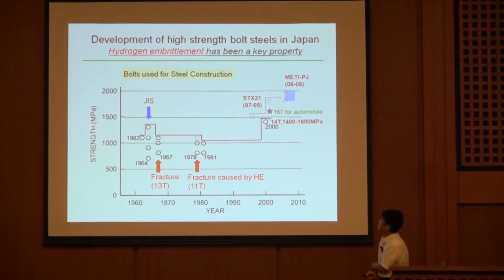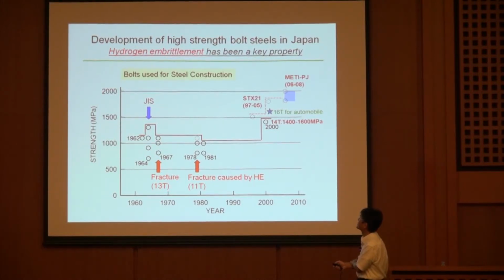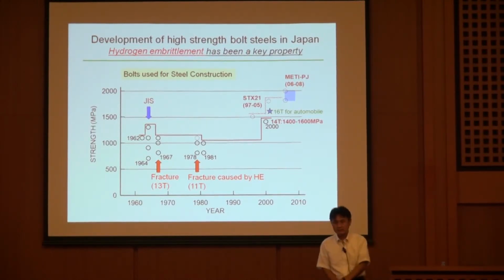Please look at this. This shows the strength level of high strength bolts for steel construction. Up to 1997, the strength level is around 1 gigapascal, and no change. Why? This is because of the problem of hydrogen embrittlement.